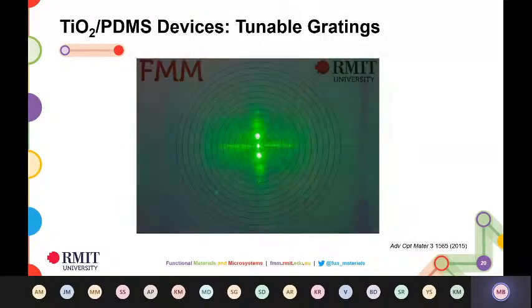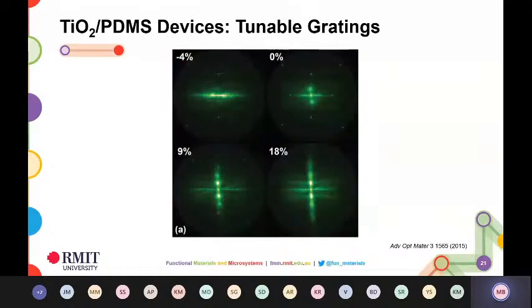What you see in this particular case is the grating sample sitting in the middle. As you see strain being applied on that sample, you're seeing a change in the diffraction patterns which you're observing from the grating. Using strain to actually tune these gratings is a novel possibility because of the fact you now have this sitting on a stretchable substrate. A similar kind of image over here: we went from -4% compressive strain all the way to 18% strain, and you can see the way the diffraction pattern of the grating is changing.